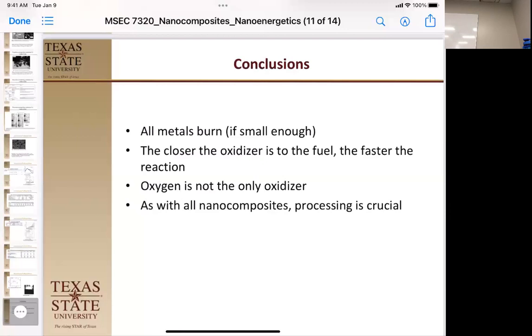As with all nanocomposites, processing is crucial, right? So if you don't process it right, it's not going to do what you want it to do. And in the case of the aluminum side, the smaller the aluminum, the smaller the fluorine source was, whether it was the perfluoroacid or the micronized Teflon or the liquid Teflon, the better results you found. So mixing and processing is critical. And that is all I have on that.